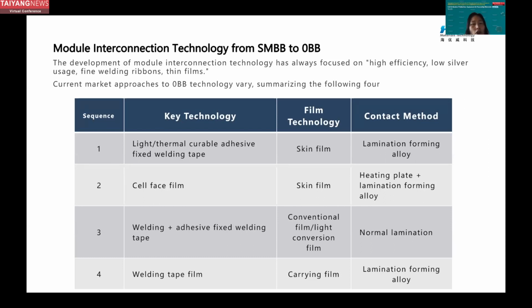The first technology is a light thermal curing adhesive to fix the welding tape and then laminated with a skin film to form an alloy. The second one is an integral coating on the surface of the cell, which is laminated to form the alloy by means of a heating plate. The third is the welding of the tape and then fixing it with adhesive, which can be achieved by normal lamination with a conventional film or conversion film. The fourth one is the technique of welding tape, lamination plus carrier film.